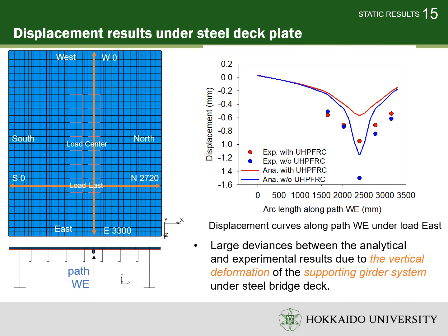Firstly, the deflection of the bridge slab is examined under the steel deck plate. The results are obtained along the path WE and path SN as shown in the left figure. From the displacement curves along path WE under the load east condition in the right figure, it can be seen that there still exists large variance in the calculated displacement.